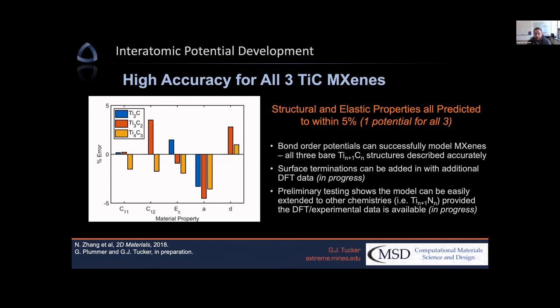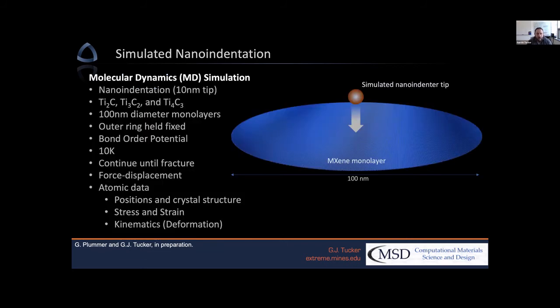Now that we have this potential developed for at least the bare MXenes, we need to use it in a larger atomistic model to probe these fundamental mechanical properties. We're going to take a couple of different examples where we can probe the in-plane and out-of-plane mechanical properties, in addition to looking at the fracture of the MXenes. This is complementary and builds upon some previous work in this area by others. So we're going to show you that here. The first thing we want to do is use nanoindentation, which basically takes our initial study and just scales it up.